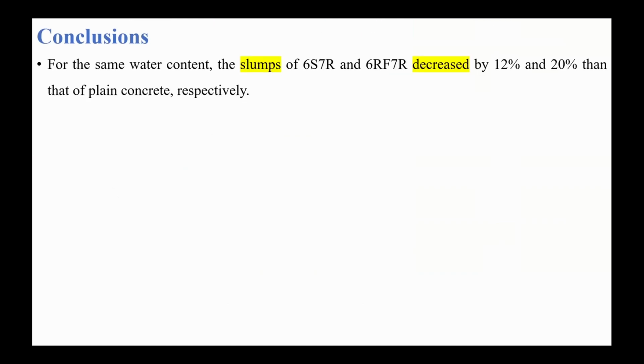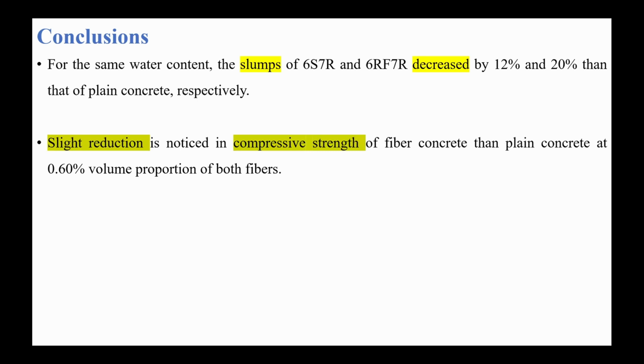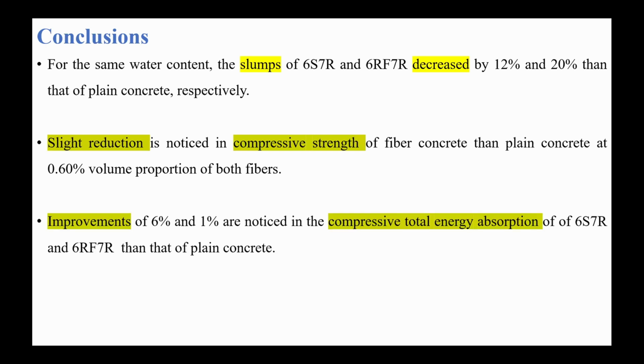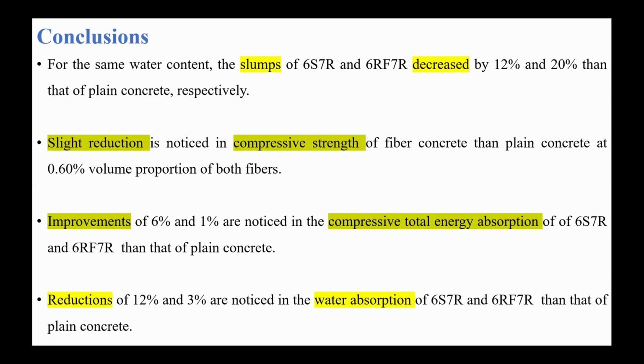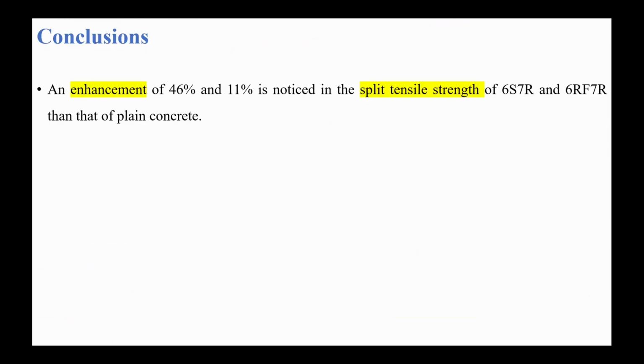Here are some conclusions from this small pilot study. For the same water content, the slumps of the 6S7R, that is industrial steel fiber reinforced concrete, and of the 6RF7R, that is the recycled fiber reinforced concrete, decreased by 12% and 20% compared to that of the plain concrete. A slight reduction is also noticed in the compressive strength of the fiber concrete as compared to plain concrete. Improvements are noticed in the compressive total energies of both types of fiber concrete, and a reduction is noted in the water absorption for both of the fiber concretes as compared to the plain concrete. An enhancement of 46% and 11% is noted in the split tensile strength.